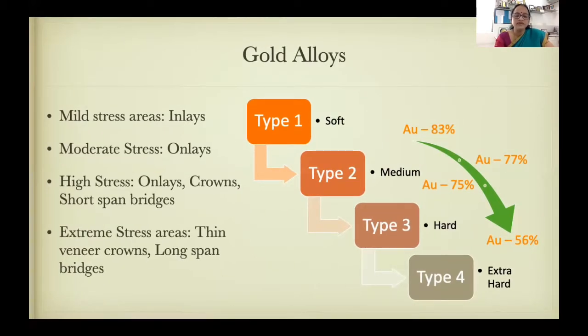Gold also is generally classified into 4 types, depending upon the gold content, which decreases as the type of the alloy increases. That is, from 83%, it reduces to 56% with type 4. And as the gold content reduces, the softness also reduces, and the alloy becomes much harder. So basically type 1 and type 2 are the ones that are used for our intracoronal restorations, because we want it to be soft so that we can burnish it. So it has to be ductile and malleable, so that burnishing is much easier. And type 3 and type 4 are basically used for crowns, short-span bridges and long-span bridges.